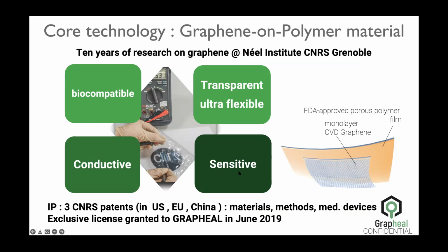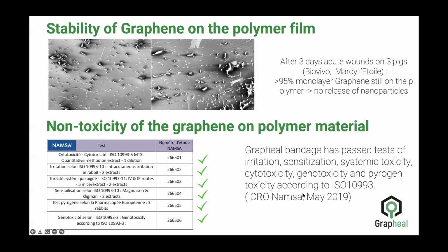And even more important is that the resistivity on the surface depends on the liquid composition on top of it. You can actually put some chemical at the interface to really orient the sensitivity towards a given analyte, towards some biomarkers. As I said, we looked a lot at non-toxicity of the material and the fact that there is no release of nanoparticle even after 3 days inside the wound on a pig model here, for example.